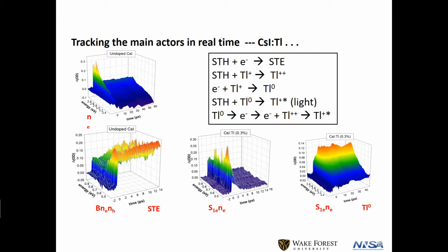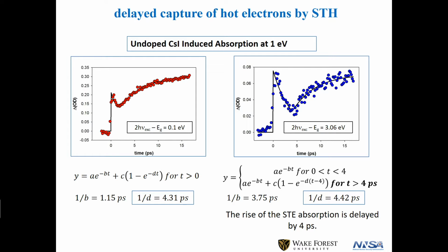And also here we see what disappeared there pops up here in the visible. These two are definitely related, and we can measure the rates. And then you get the light, the thallium light that's not quenched at room temperature, comes from these two, and I'll just label this as, we call this reaction 2. The self-trapped hole moves around and finds the thallium 0 and gives you light. Or the thallium 0 later releases an electron. That's how come it's slow, the sodium iodide problem. It's these late-term releases going on. And the electron finds this thing that you made and stored the hole, and then that gives you the excited state and you get the light. So those are input data for the model.